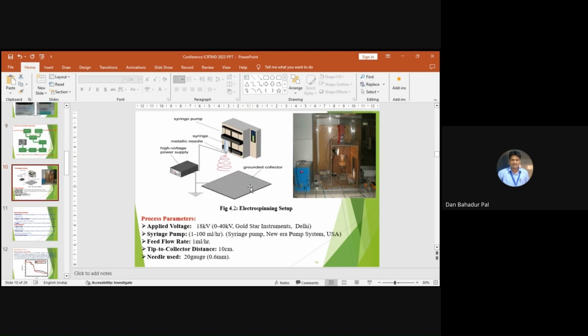This is the electrospinning setup where we have applied a high voltage between the needle tip and the collector plate. Through that the nanofiber will be prepared. Here the applied voltage is around 18 kilovolt, and the syringe pump range is 1 to 100 ml per hour, but the feed rate will be 1 ml per hour. The collector to tip distance we have taken is 10 centimeter, and the needle gauge is 20 gauge, that is the diameter of the particular needle.